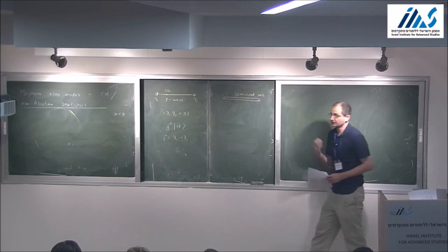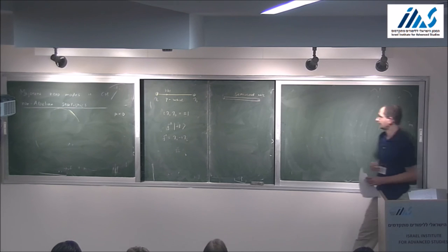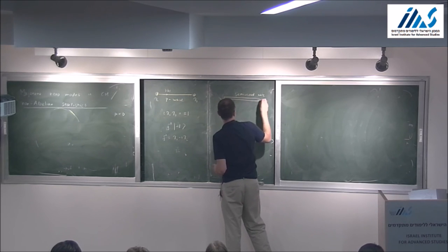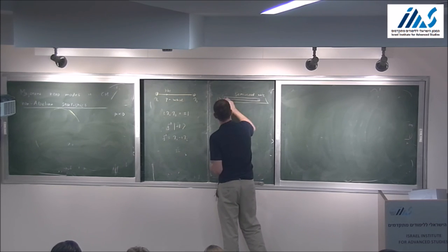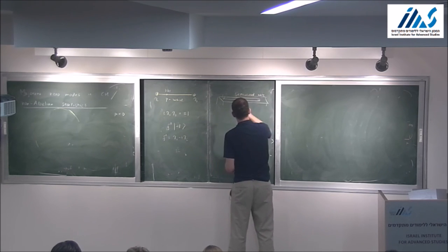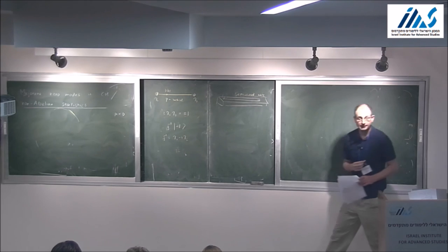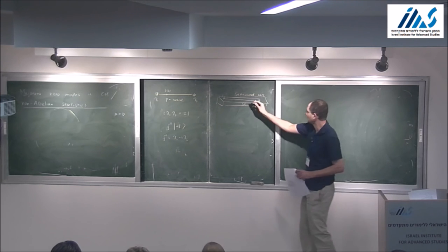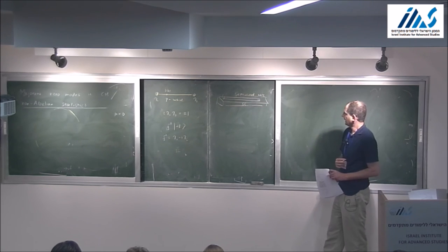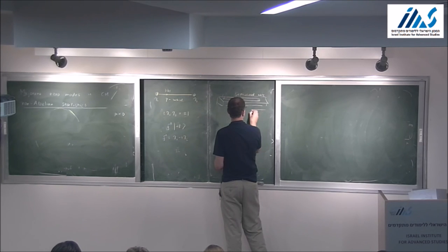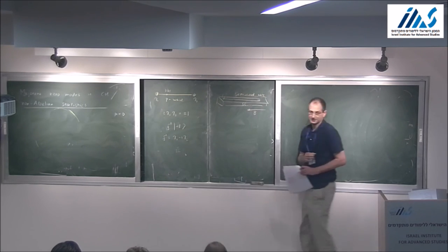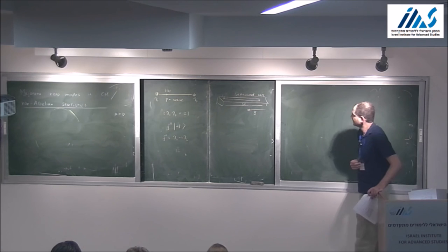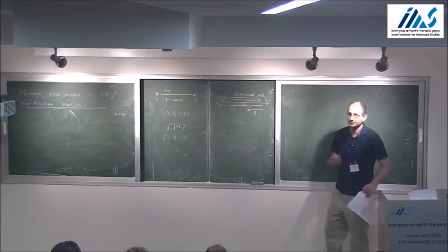The semiconductor by itself is not superconducting. It's like a 1D electron gas, but it's proximity coupled to a superconductor. So you can imagine that there's some thin superconducting substrate. So this would be a superconductor, and in the new versions it's actually a very thin coating of superconductor on this semiconducting wire. And now there's a big magnetic field which is applied in some direction. Clearly the two ingredients to realize this phase are to have superconductivity and to have a large magnetic field applied.